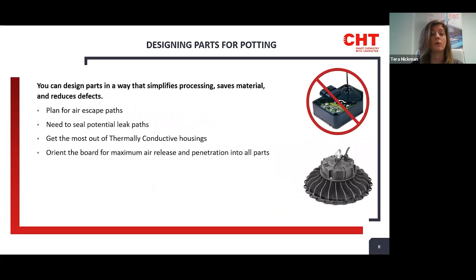The design of your components is as critical as selecting the right material. When designing your part — whether it be an LED driver or the boards themselves — you must plan for a path for air to escape as you're filling the part. Stay away from 90-degree corners in the housing, and add through holes for air release to prevent air entrapment or voids. You want to fill the part completely to avoid future failure. Design the board with a planned material injection point. Also expect leaks — wires may need to enter or exit the potting. Ensure the points of entry are sealed, including sealing the heat sink.